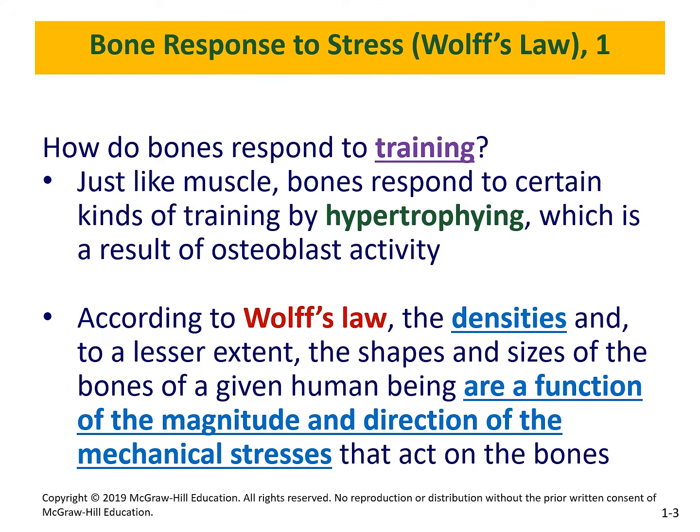We had incidences where the stem of the total hip comes out through the skin because it just cracks inside the body, because the bone around it is now very soft and the implant is very strong. The osteoclasts say, well, why do we need the bone around it if the implant is holding the stress? So that's called stress shielding.